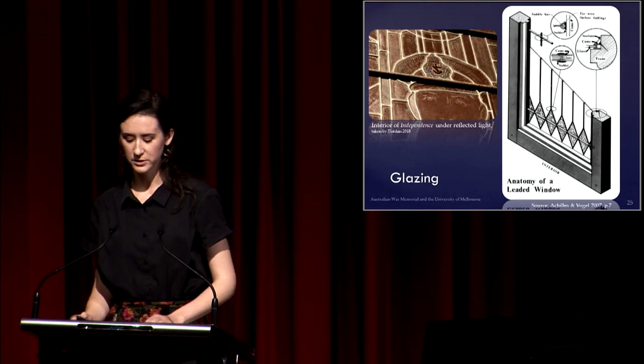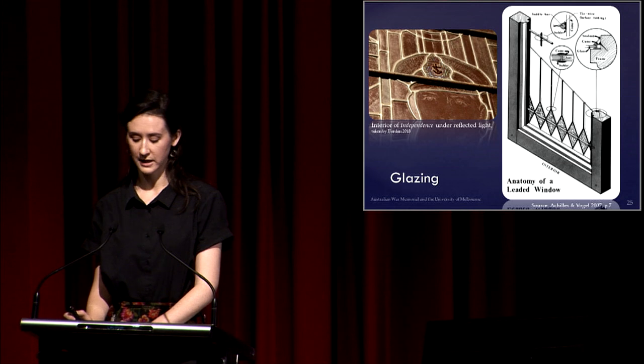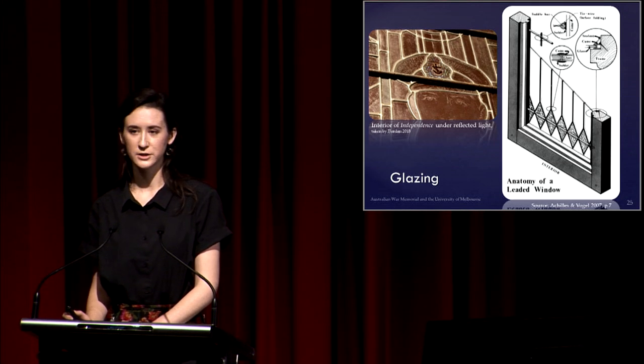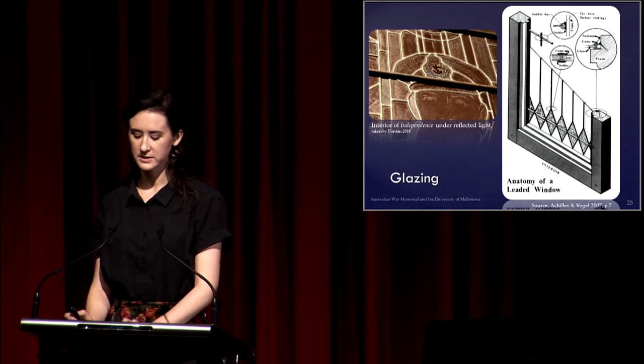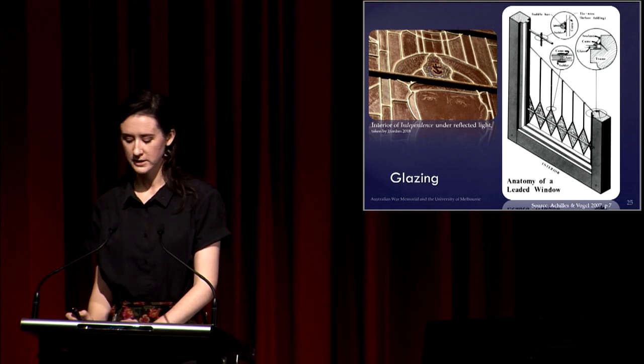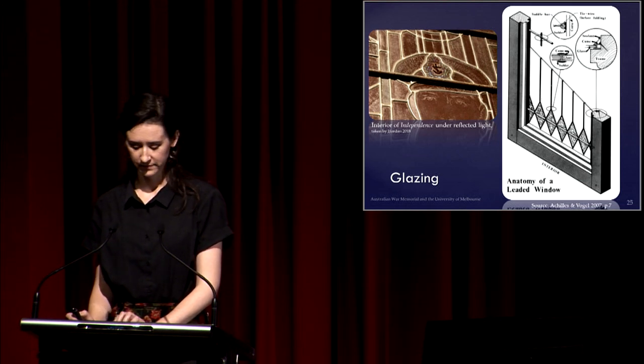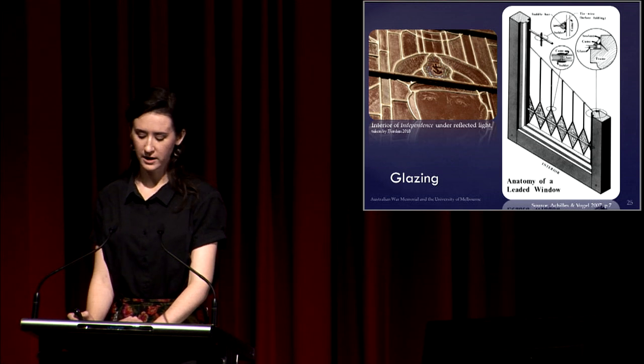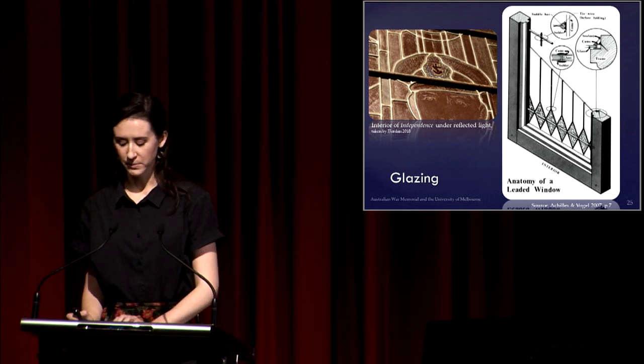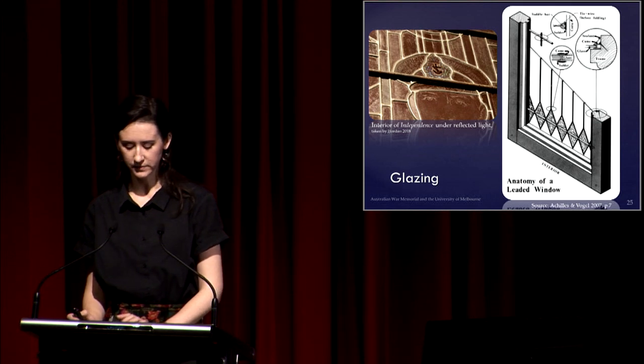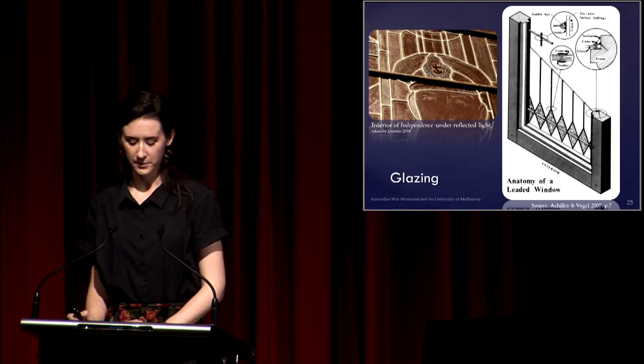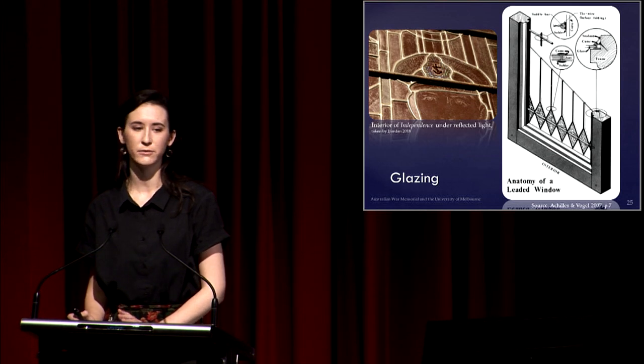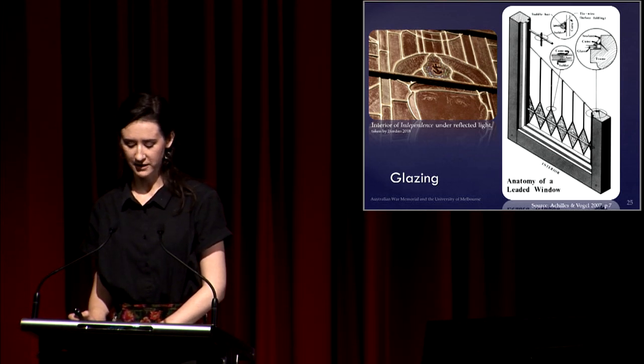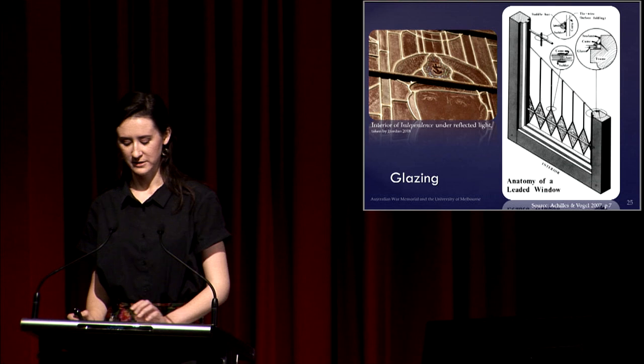After firing, Mr. Anderson assembled the glass into H-shaped lead strips called cames, then soldered the joints and used a glazing putty for weatherproofing. The photo of Independence here and diagram pictured give you an idea of how the glass and lead fit together. The putty is a combination of chalk and or plaster of Paris with lamp black for colouring, red lead to harden, and all bound together with linseed oil. The panes were glazed in small panels about 50 by 40 centimetres each. Waller helped out near the end because, as he stated frustratingly in a letter to the memorial, he felt that Mr. Anderson was moving much too slowly.